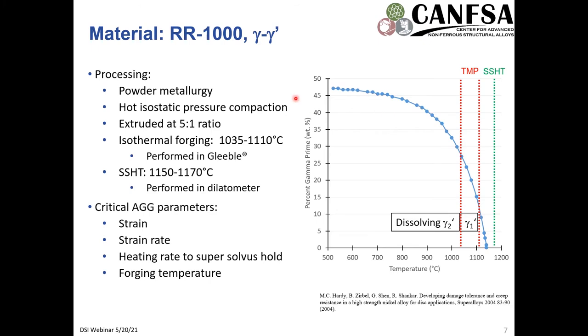And so the material I'll be focusing on is RR-1000, a Rolls-Royce alloy, and this is a gamma gamma prime alloy, as I mentioned. And processing for this, instead of having a cast starting condition, we're going through powder metallurgy, and then it undergoes a HIP, or hot isostatic pressing, compaction and an extruding at a 5-to-1 ratio. And then there's isothermal forging that occurs at this near solvus but still sub solvus temperature, 1035 to 1110 Celsius. Sometimes these temperatures may get a little bit hotter. For a lot of my experiments, we started going towards 1110, 1120 Celsius. And I've been recreating this condition with specimens in the Gleeble, as I'll talk about.